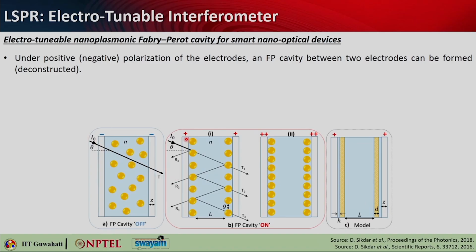But as soon as you make the electrodes positively charged, what will happen? The negatively charged nanoparticles will come and assemble on top of these electrodes, and they will start forming a 2D array. And as they keep on getting denser and denser, the reflectivity of the 2D array will get stronger. And that is the reason why I have shown those kind of 2D assemblies.